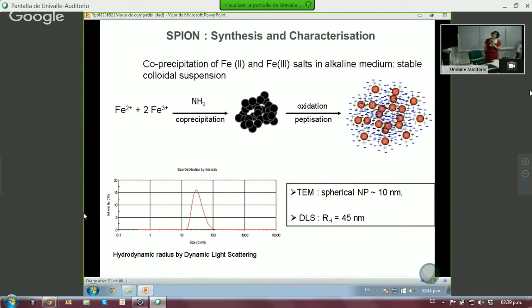So this is the method we used. We used iron 2 and iron 3 salts in an alkaline medium, and both of them co-precipitate and you get the nanoparticles. Then they come into a colloidal suspension, essentially. And the aim is to keep them well separated and not have them gather together, but I think this is now very well controlled. We determined the hydrodynamic radius by dynamic light scattering. We also used TEM and DLS, and we got all these numbers.